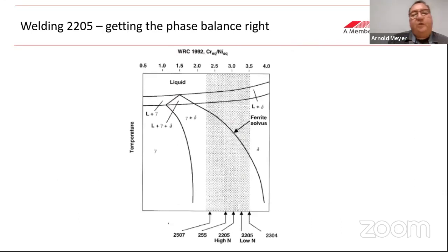Then, if we quickly look at this phase diagram, you will see there, if I move my cursor, where your high nitrogen 2205 and your low nitrogen 2205 are, and that is what we're looking at. This weld metal solidifies first of all as ferrite. In other words, you have solid here that is 100% ferrite. On this line, the ferrite solvus line, upon further cooling, you start forming your austenite, your gamma.